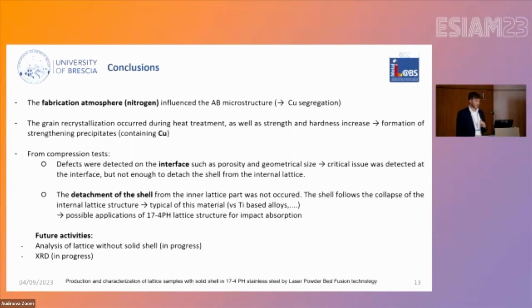The critical issue was detected at the interface, but not enough to detach the shell from the internal lattice. So, as I said before, we can obtain a good deformation of the shell that follows the compression. The detachment of the shell from the inner lattice part did not occur, and the shell follows the collapse of the internal lattice structure, typical of this material, as I said before, and of another study that I presented for the titanium-based alloy. A possible application of 17-4 PH lattice structure is for impact absorption, given the typical and classical deformation of the shell that we can see.